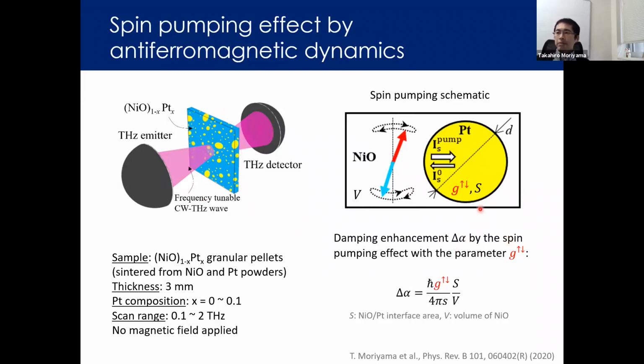So the detailed schematic of the spin pumping diagram is shown here. Basically, the nickel oxide dynamics would pump the spin current into the platinum granule. The spin current will be dissipated due to the spin orbit interaction in platinum, which basically results in the loss of spin angular momentum in the system. Therefore, if we measure the damping constant, we should observe the enhancement of damping constant described by this equation, where G up down is the so-called spin mixing conductance. This is a parameter which characterizes the spin pumping effect. And S is the nickel oxide platinum interface area, and V is the volume of the nickel oxide. So by increasing G up down or this interface area S, we should observe the increase of the damping constant.